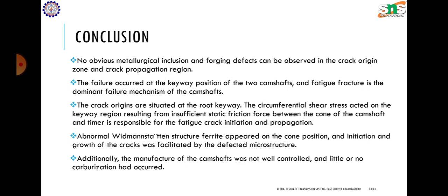The second one is that the crack initiated at the root of the keyway by means of insufficient static friction force, so it initiates fracture and propagates. Then the third reason is the abnormal microstructure, that is, Widmanstätten structure ferrite appeared on the cone surface. So these three things cause the fatigue failure of the camshafts.